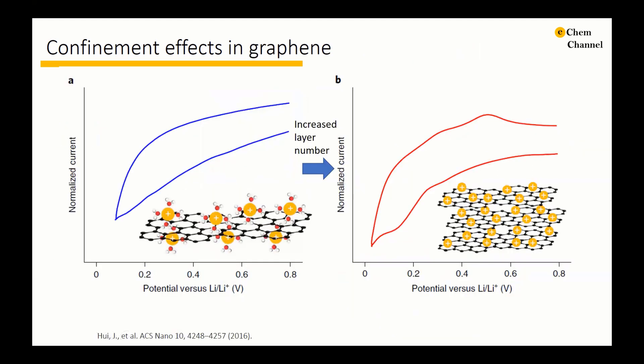The two examples demonstrated that confinement may cause deviation of pseudo-capacitive materials. How about graphene, a non-pseudo-capacitive material? The CV of single-layer graphene shows a capacitive current response in an organic lithium-containing electrolyte. Such response could arise from the adsorption of solvated or partially solvated lithium at the outer surface of single-layer graphene. However, starting from the fourth layer, the redox peak associated with intercalation of desolvated lithium emerges in the CV curve. When the number of layers increases, the interlayer space between two graphene sheets decreases, and the interaction between the host and the lithium ion increases, leading to mechanism deviation.